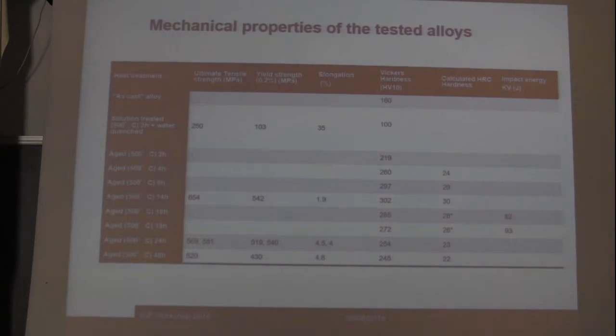As you can see, after aging for 14 hours, we had a yield strength of 540 megapascal and a Rockwell hardness of about 30. But unfortunately, we had an elongation of only about 2%. So selecting this material could be a concern for the production of the screws.